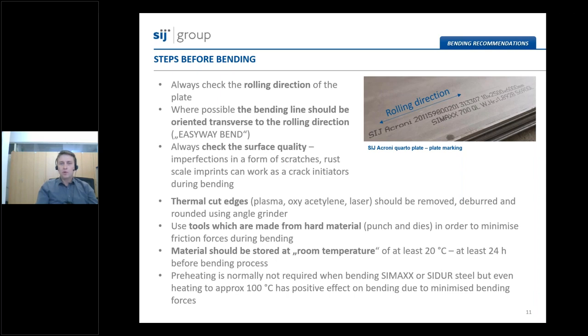As was already discussed in the cutting webinar, thermally cut edges from plasma, oxyacetylene, or laser cutting should all be removed, deburred, and rounded using the angle grinder. In the case of, let's say, very hard steels like SIDUR 500 grade, the heat-affected zone due to the thermal cutting process can be very hard and therefore can act as a crack initiator when bending with a really small punch radius is used.